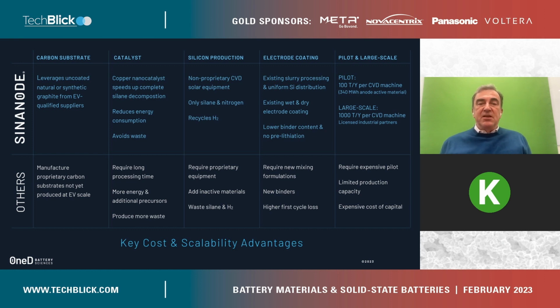So what is different from any other silicon solution is, first, the carbon substrate exists. It's EV grade graphite. Second, we have a patented process to make a copper catalyst so that we can reduce the amount of energy needed and we can speed up the reaction. And all of the silane is decomposed.